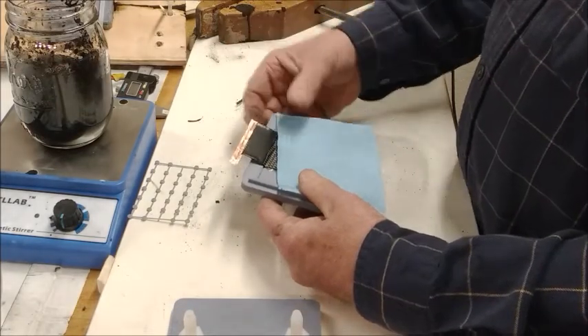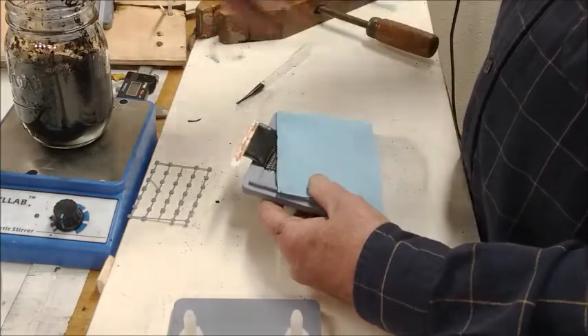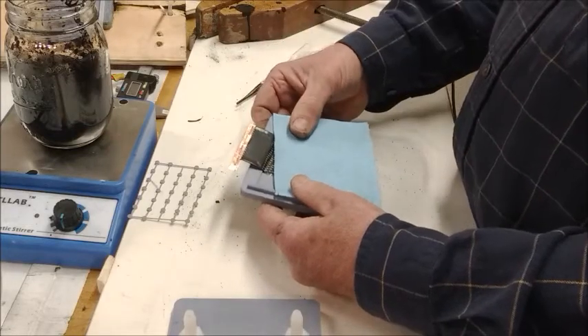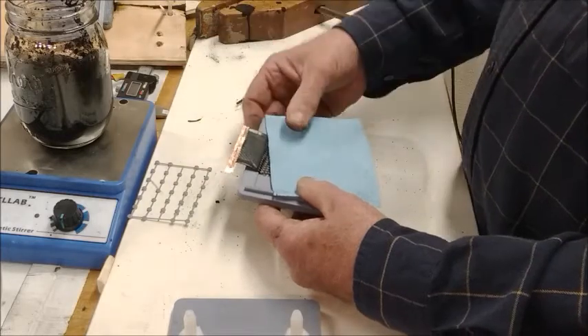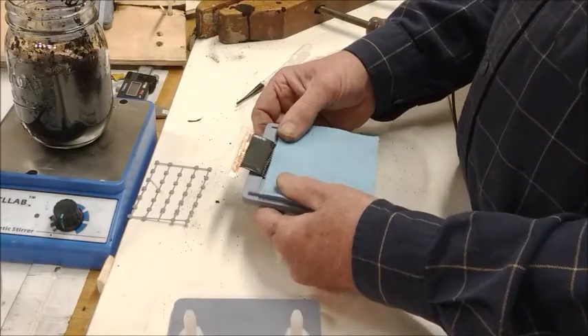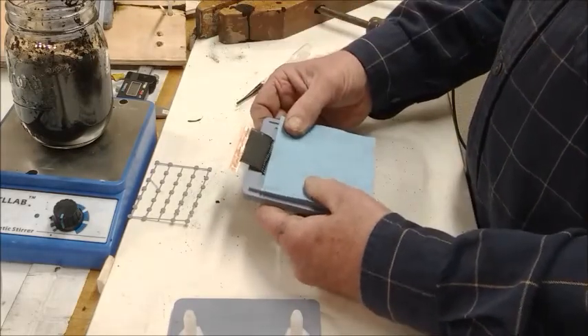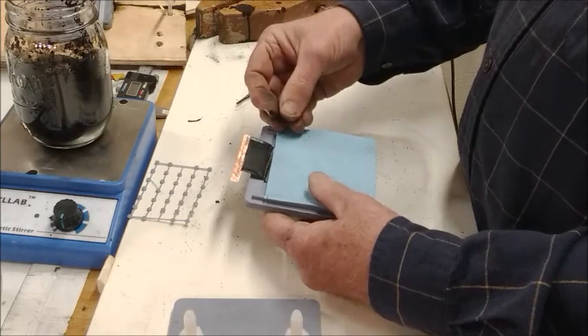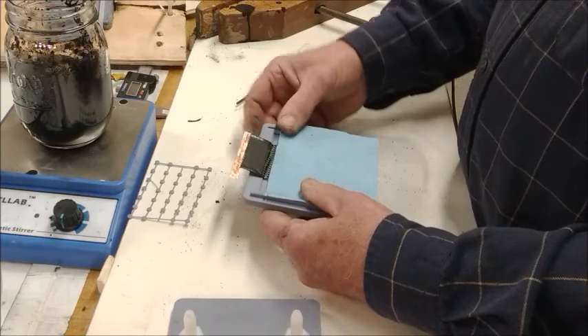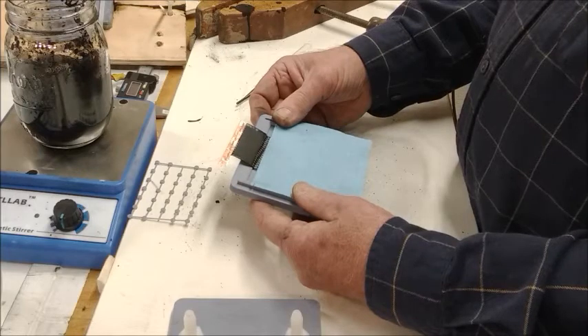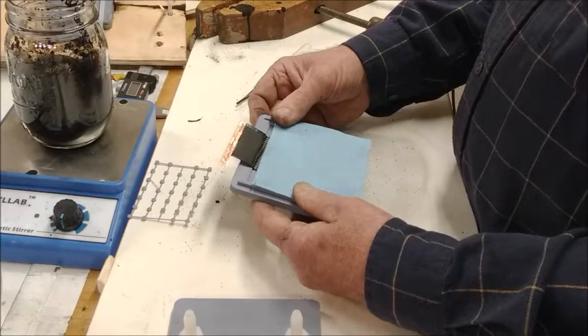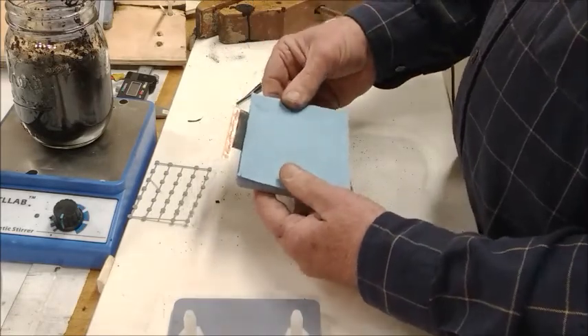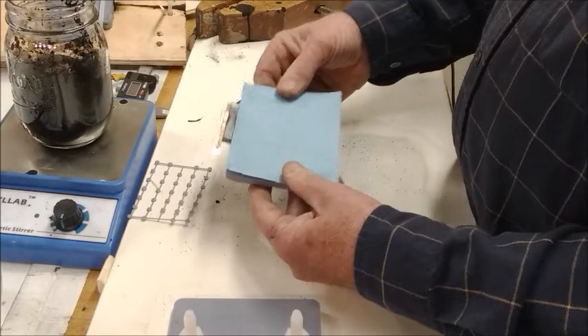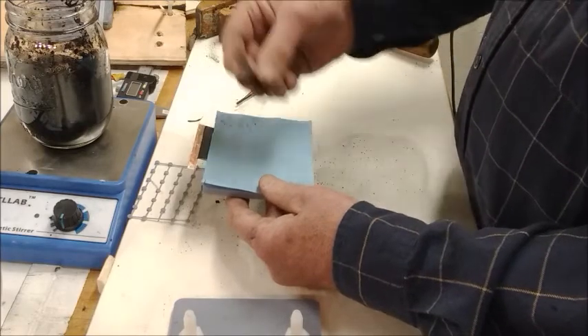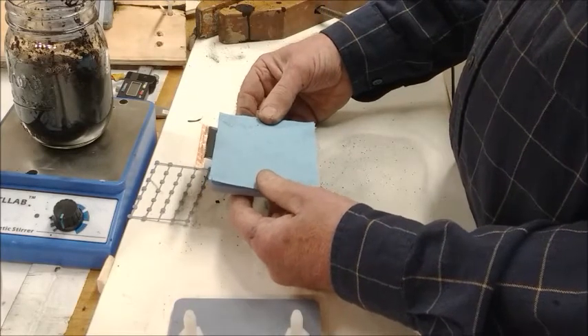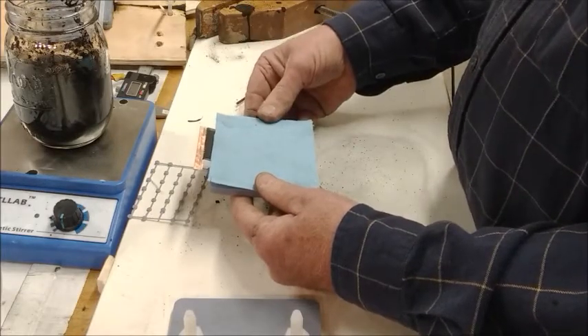Depending on the concentration of the suspension, less concentration lowers the viscosity to make it more flowable, but also means the particles are further apart, harder to receive the charge, and the overall capacitance is decreased. So we're playing with the trade-off between viscosity, concentration of solids, and conductivity of the carbons, and the next step in my test is to go with about a 1 millimeter gap. Unfortunately, the same sponge-like paper towel, and I say sponge-like because as this thing gets wetted, it soaks the liquid portion of the electrode out, leaving the solids portion. Now the solids viscosity is higher and it doesn't flow.